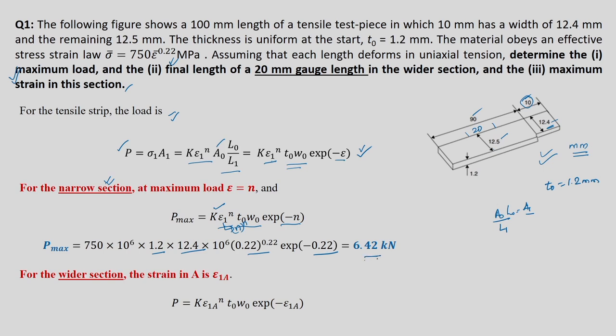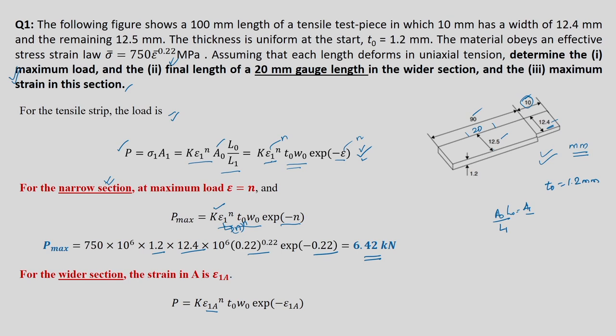P_max comes to about 6.418 kN, so it is 6.42 kN. We are simply modifying the equation for maximum load: at epsilon equals n in the narrow section, epsilon₁ becomes n, and exponential minus epsilon becomes exponential minus n. So we can write directly: 750 times 1.2 times 12.4 times 0.22^0.22 times exponential minus 0.22 gives 6.42 kN.